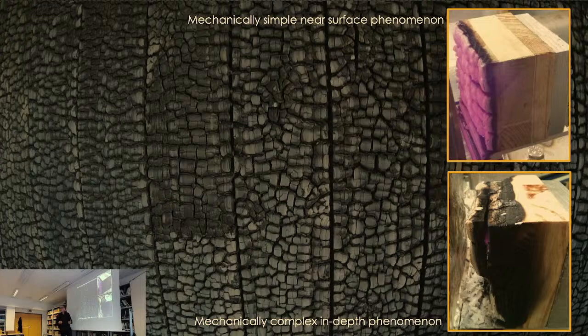Okay? So in essence, going back to extinction, what you need to do is basically guarantee self-extinction as soon as possible. Okay? Now, you're going to say, well, but you cannot control how much fuel you have in a compartment. No, you can't, but you can control the geometry. So if I make a compartment taller, or I change the ratio of the windows and doors and things of the sort, I can actually change the thermal environment. And I can make sure that the decrease of critical heat flux happens very fast. And as a result, I get a very, very thin char layer that gets formed before self-extinction occurs. And then the process becomes one that enables you to circumvent everything.